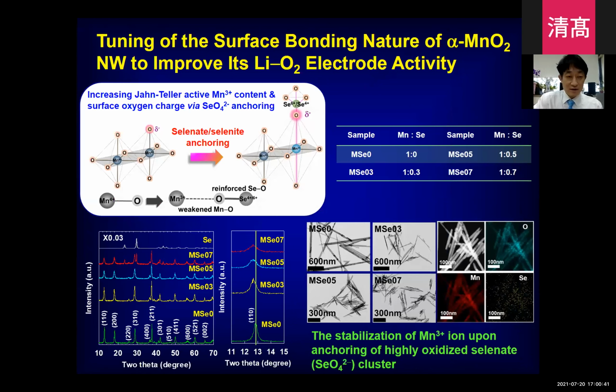Okay, let me show you another example. We try to immobilize the selenite nanocluster on the surface of manganese oxide nanowire. As I told you, the stabilization of manganese 3+ is very important. But as I told you before, manganese 3+ can be stabilized in a tetragonally elongated octahedral environment, because manganese 3+ is a Jahn-Teller active ion.